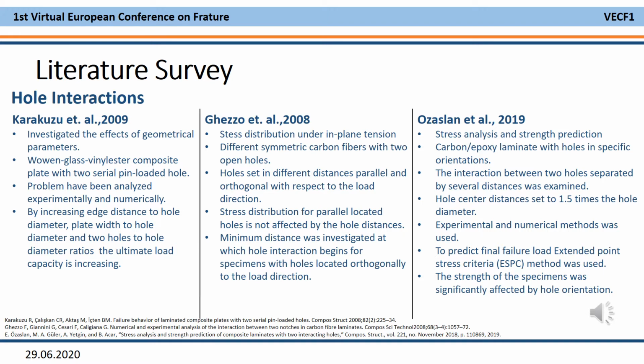Then Ghezzo et al. analyzed the stress distribution under in-plane tension loading between two open holes that were set parallel and orthogonal, respectively, with respect to the load direction for different symmetric carbon fiber laminates. They concluded that the stress concentration factor is not affected by the distance between the hole centers for specimens with holes located parallel to the load direction. Moreover, they investigated the minimum distance at which hole interactions begin for specimens with holes located orthogonally to the load direction.